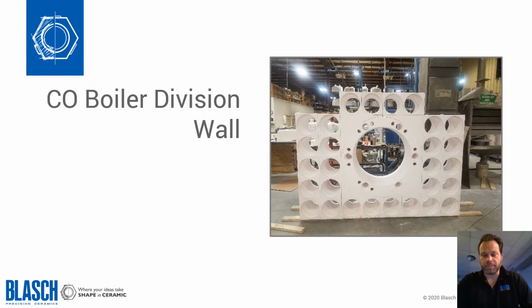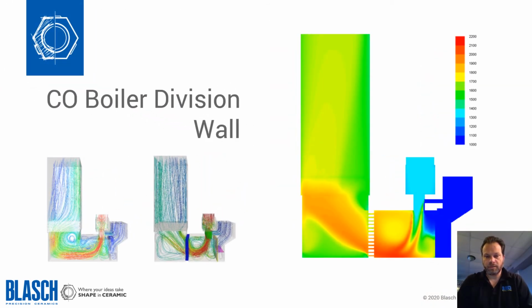Using our know-how and experience we've developed over the years with our hex wall and vector wall systems, Blasch engineers came up with a diffuser wall in a CO boiler, pictured here. For this particular customer, they were experiencing non-uniform flow path, pictured on the bottom left. By implementing this diffuser wall, which is a series of interlocking tongue and groove brick shapes with an engineered hole, Blasch engineers were able to distribute and break up the flow uniformly.